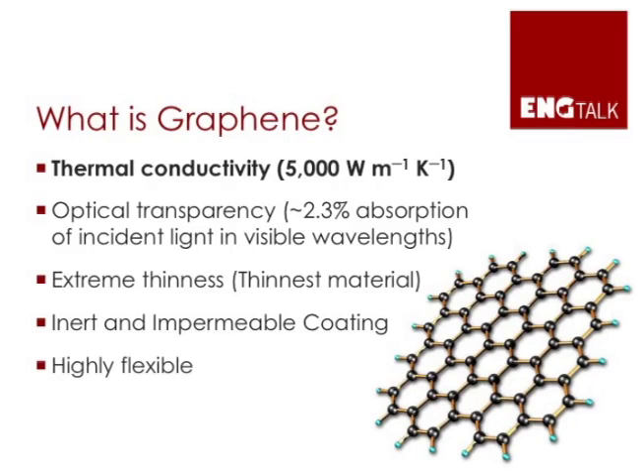If you have an ideal freestanding floating graphene sheet, electrons are definitely very mobile in graphene. The thermal transport properties are excellent — 5,000 watts per meter Kelvin is one of the best in nature, but again, this is only true for a suspended graphene sheet. Once supported on a substrate, you see leakage effects and this number drops. Graphene is optically transparent, inert and impermeable — nothing can pass through it — and it's highly flexible, so you can bend it and twist it.